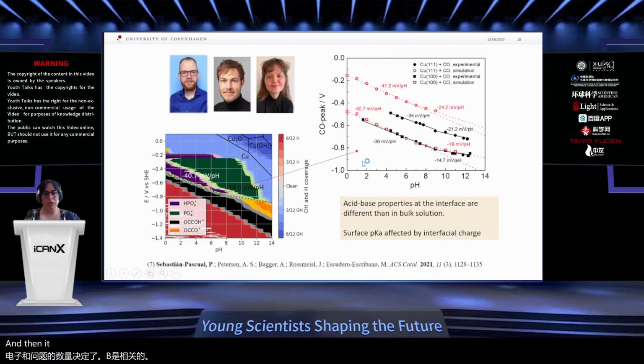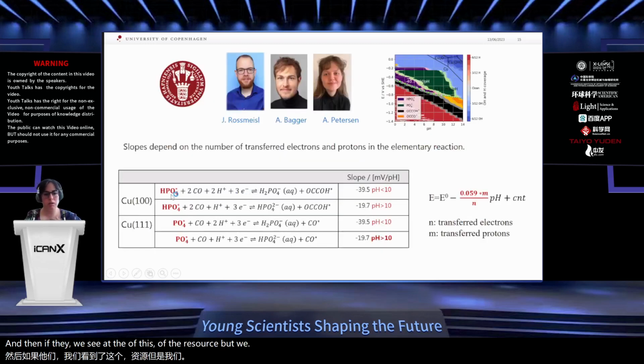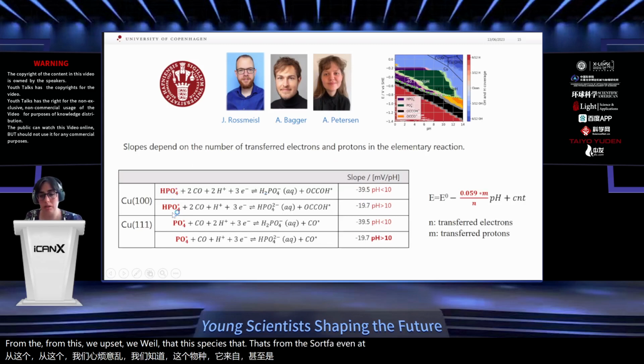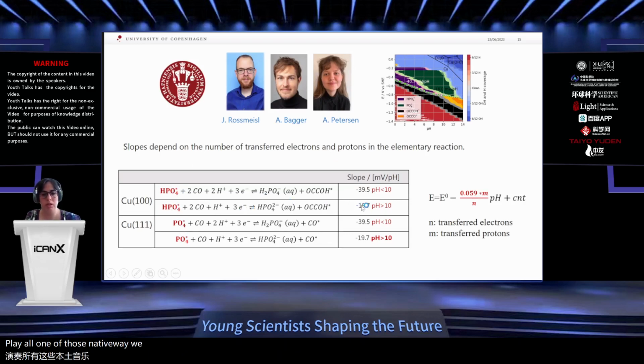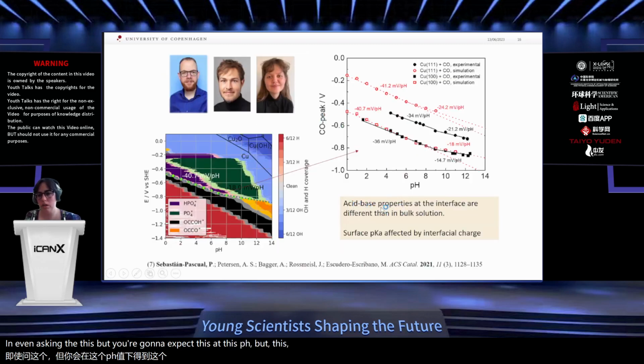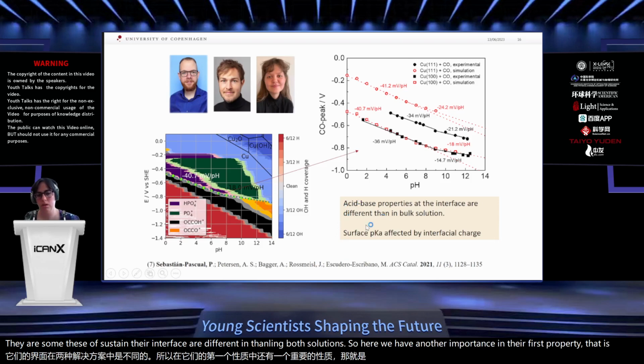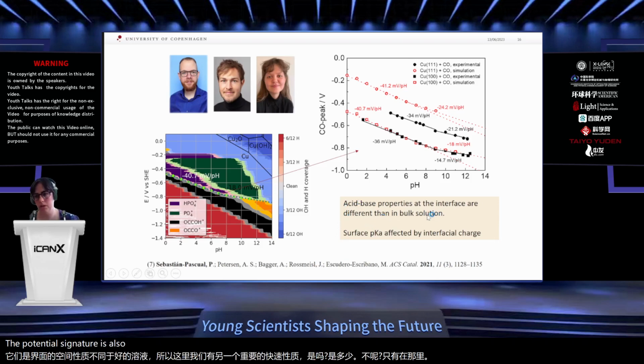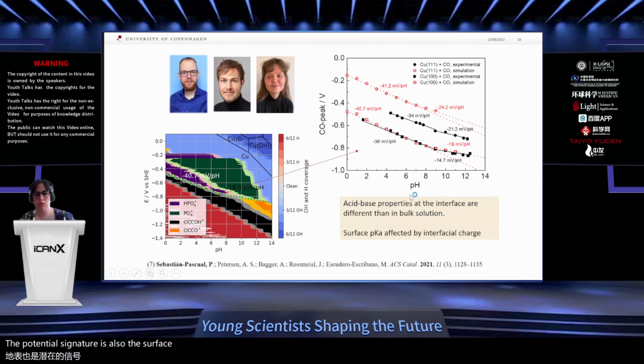And then if we look at the results to understand this, we conclude that the species that are adsorbed on the surface, even at acid or neutral pH, are phosphate or monoprotonated phosphate species, which you find even at acid pH, despite that you don't expect this at this pH. But this is indicating that the acid-base properties at the interface are different from those in bulk solution. So here we have another important interface property, not only the potential of zero charge, but also the surface pKa, which can be affected by charge distribution on the surface.